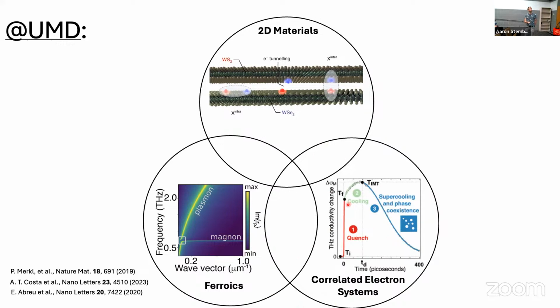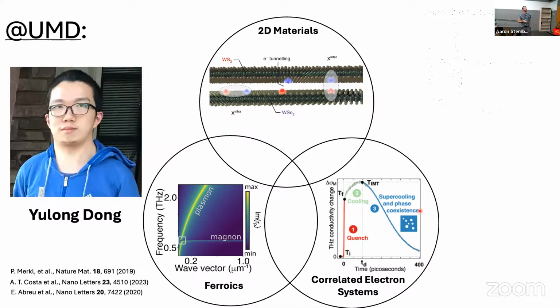So this is data from Richard Averitt that suggests that not only does nucleation and growth cause inhomogeneity in phase transitions, but also supercooling processes, for example, in neodymium nickelate, can lead to phase separation that creates bottlenecks for how the system can recover back into its parent state.